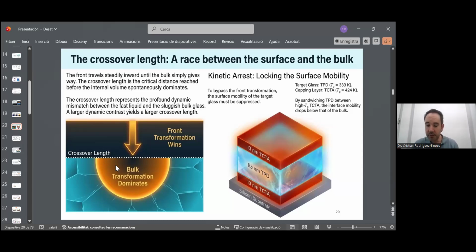Now, imagine that we want to study the bulk transformation of ultrastable glass. In fact, this is what we want to do. We are not interested in surface effects. We want to study the bulk transformation. So we have two strategies. One is taking advantage of this: instead of growing 100 nanometers, we grow 1 micrometer or 10 micrometers. In that case, of course, the transformation will start from the surface, but since it has to travel a very large distance, eventually the bulk transformation will dominate. So if the film is thick enough, we can neglect the effects of the front transformation. This is one strategy.